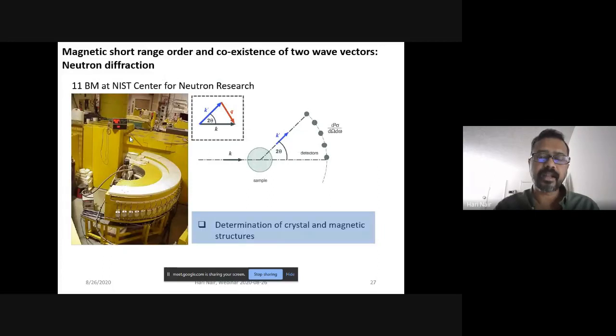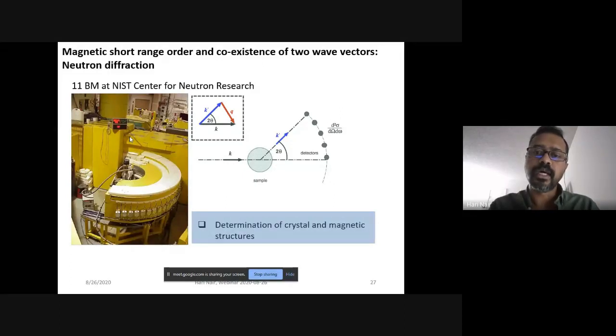So then we try to do a direct determination of the magnetic structures. For that, we do neutron diffraction experiments at national labs, for example, at the NIST Neutron Center. This is nothing but a scattering experiment. The schematic shows a sample in the area marked by a circle, and the incoming arrow indicated K is the wave vector of the incoming neutrons, which is 2 pi by lambda. So it's in a way the energy of the incoming neutrons, and then it gets scattered from that circle and becomes K prime, the scattered neutron.